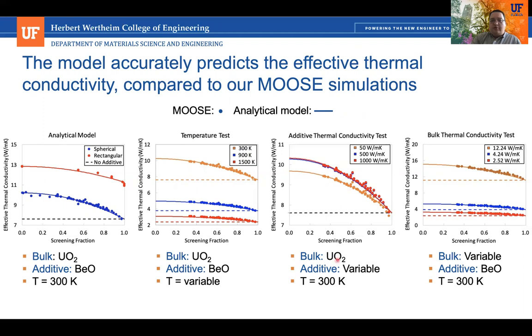Now here we've kept UO2 at 300 Kelvin, but now we're changing the additive. So we have 3 different thermal conductivities of the additive that we're trying, and we're increasing that. And again, the model performs very well, but we get some interesting results here, where we're showing that there comes a point where even if you increase the additive thermal conductivity even more, you don't get any additional benefit. We sort of hit a threshold where we can't get any better, even if you double the thermal conductivity of the additive. And then the last case, we have a bulk thermal conductivity that's changing, but we're always using the additive thermal conductivity of beryllium oxide at 300 Kelvin. And again, the model is performing well.